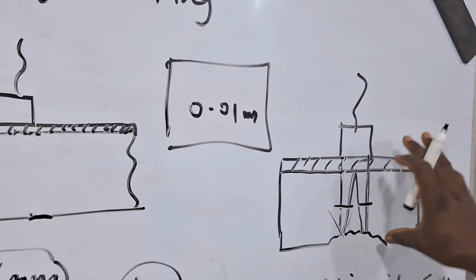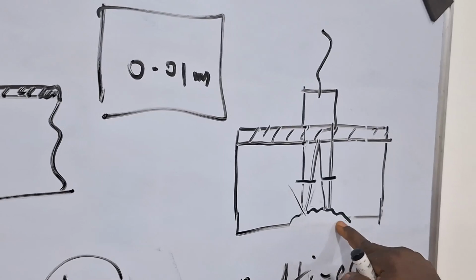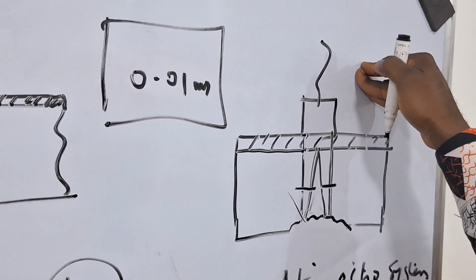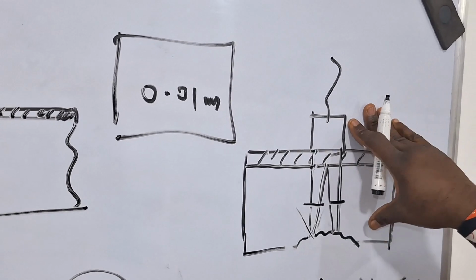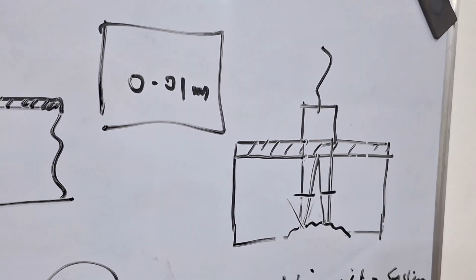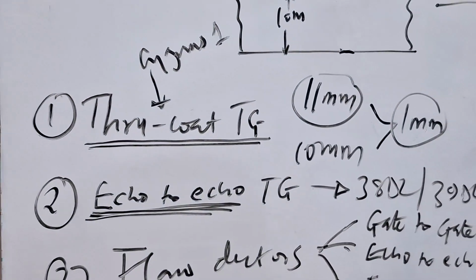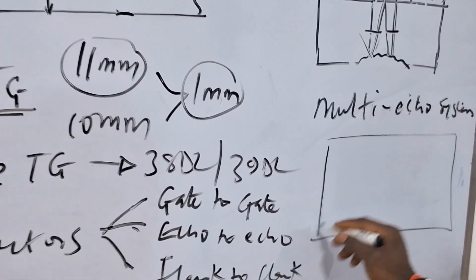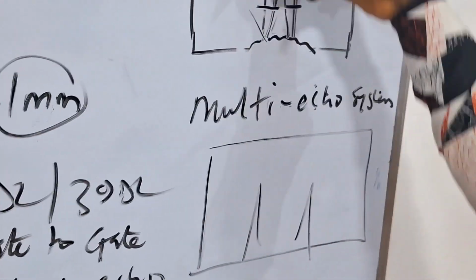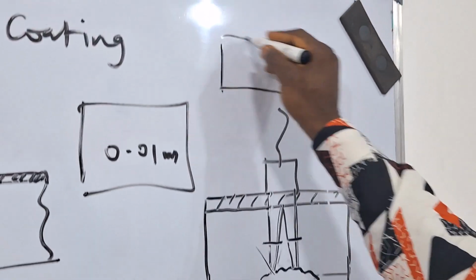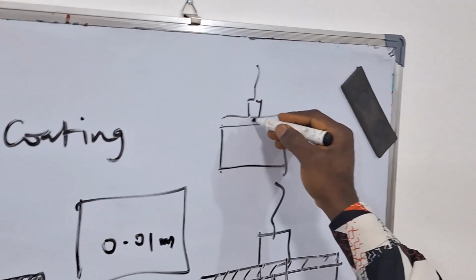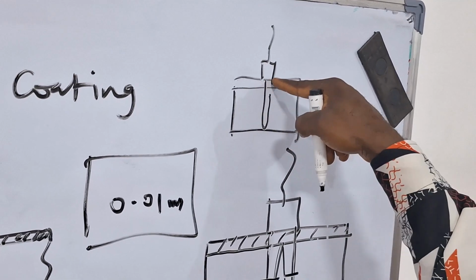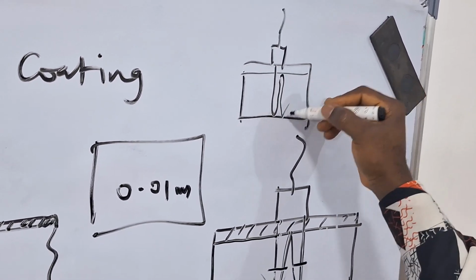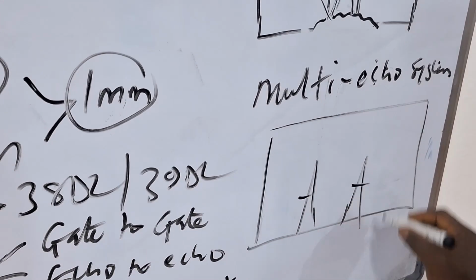So one thing that this multi-echo method does is it relies on a smooth backwall surface for you to get your final result. But if the surface is clean and everything is right with the unit, it will automatically give you the true coating thickness of the material through this multi-echo system. In the other case, with the echo to echo, normally if I have a unit, even if it is coated and I have my probe, when this thing goes, it comes back. When it gets to this surface, it is reflected back, thereby leading to multiple echo.